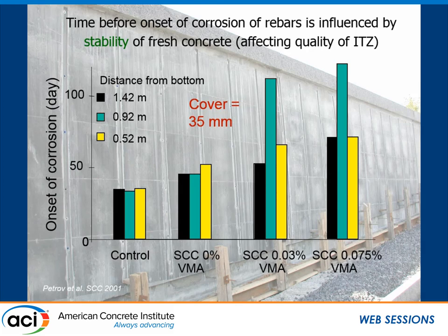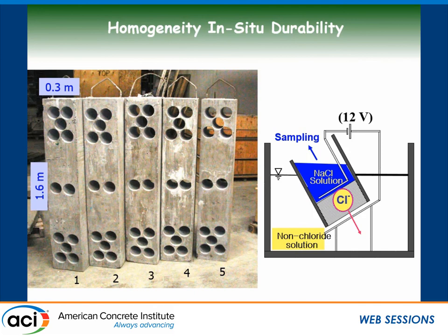The same thing happens near the bottom, so it goes higher and higher. And in the middle, it's even the highest. So building surface settlement resistance, building viscosity, is increasing this. Okay. And if you want to convince yourself a little bit more, you can cast different columns and take some cores into them and look at diffusion coefficient. Actually go and do some diffusion coefficient testing of the cores.